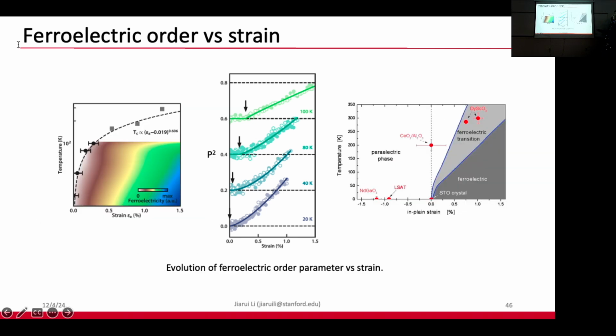And then when we look at this ferroelectric order parameter as a function of strain, we find that it is a second order phase transition without a very sharp jump. And they also have very highly temperature dependent critical behavior. You see that they have a very large curvature at 20 and 40 Kelvin, but they straighten out at higher temperature, around 100 Kelvin.